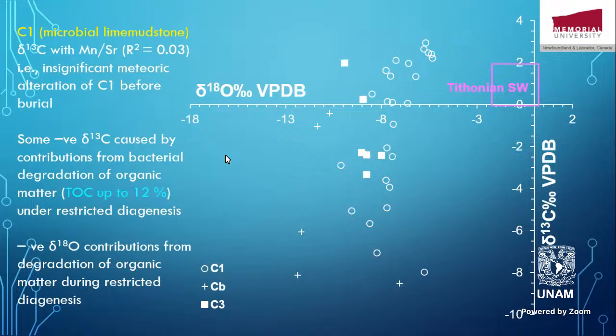So even under restricted diagenesis, if you have lots of carbon dioxide there, it will bring the delta carbon 13 signature down. Well, then the negative delta oxygen 18 contributions come from degradation also of the organic matter during the restricted diagenesis. So it could be the negative here. As I said, it's too depleted compared with the best preserved delta carbon 13 material of the Tithonian carbonates. You can see here delta carbon 13 close to minus 8 or so. This is too much. Delta oxygen 18, forgive me, it's minus 8 or so for the lime mudstone. You get minus 8 delta oxygen.